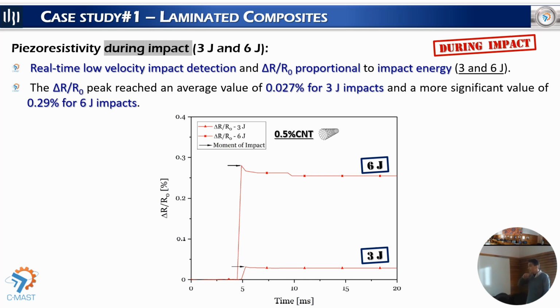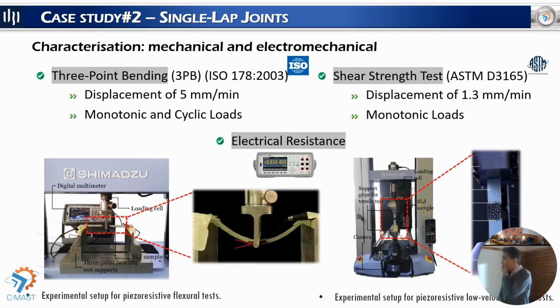So the samples were able to detect the presence of an impact, and also by measuring the electrical resistance variation, we can have an idea about the energy that was involved in this impact. So I would say that these results show that we are on a good way to produce self-sensing composites that are able to detect the presence of damage in real-time application, or also in an inspection post after the operation of the structure.